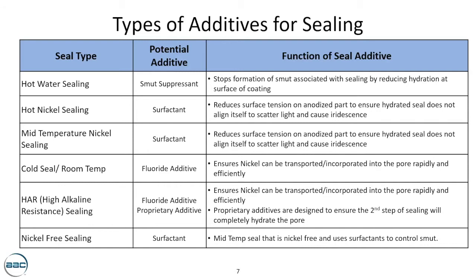Cold seal and room temp sealing. So the primary additive here is a fluoride additive, and the fluoride is used to transport that nickel from the cold seal solution into the pore. If fluoride isn't managed correctly, you won't get enough nickel in the pore, and you likely won't pass blue dye stain testing. So this type of chemistry is extremely popular because it lends itself to not having to use any sort of surfactants. So there's no risk of consuming or breaking down a surfactant disproportionately.